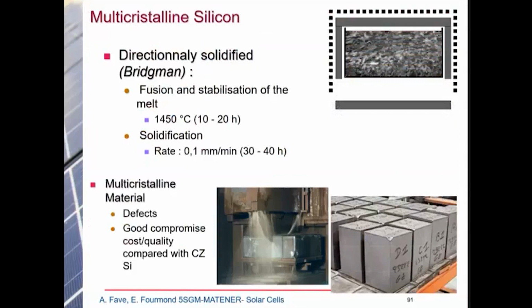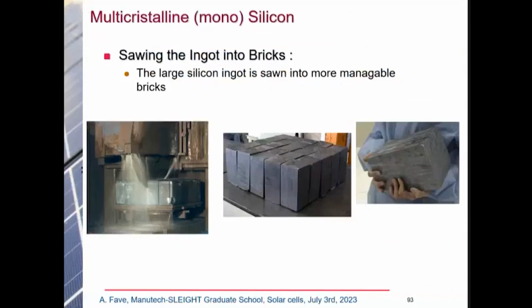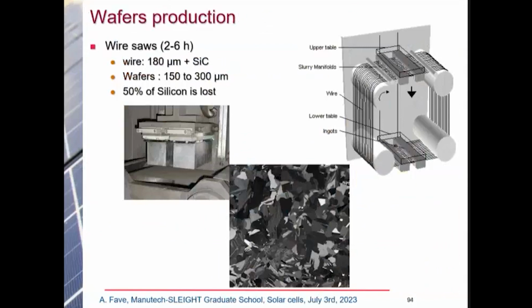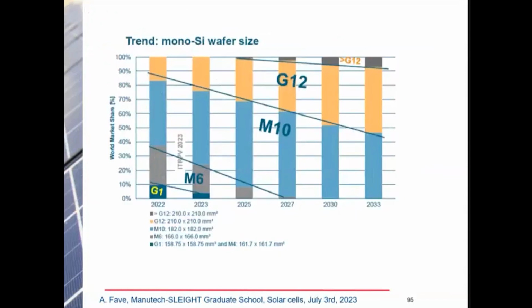Once you get your ingot, you cut it in pieces. Okay. Then you slice. You make wafers from 150 to 300 micrometers. During this step, actually, it's important to know that you lose about 50% of the silicon because of the diameter of the wire. The size of the wafers was standard until recently. It was 166 millimeters square, and now we have more and more wafers with a larger size, and now we are starting to use them. So 21 by 21 centimeters. So we are increasing the size of the wafers.